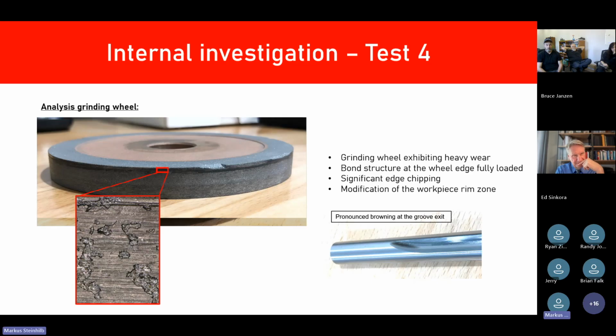When we inspected the grinding wheel here, we see that the grinding wheel showed strong wear. The bond at the wheel edge was fully loaded and glazed, and clear edge chipping was visible. In addition, changes were seen in the outer area of the workpiece.